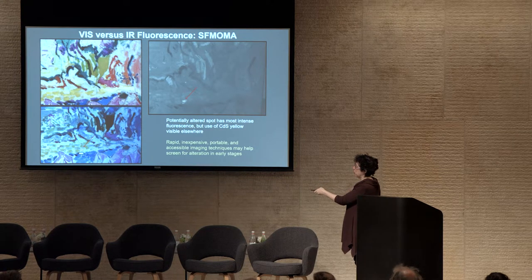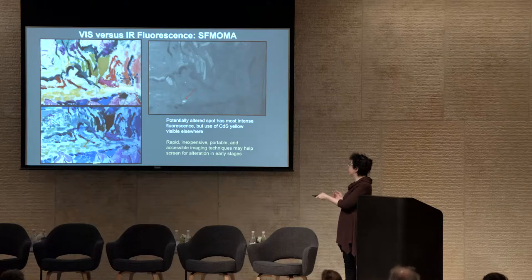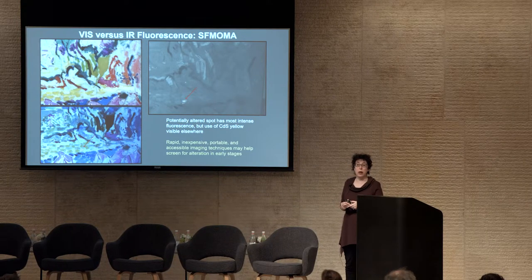The same thing is true in the area below the central reclining figures — that one brush stroke that looks a little dirty shows up as orange in ultraviolet light and as bright white in the infrared. Even if you just have an ultraviolet light you can buy on Amazon for about $30, we have an incredibly accessible way to understand the state of preservation of these paintings. This problem is largely confined to the period from the 1880s to the 1920s but has become a phenomenal problem for the works of the Impressionists, Post-Impressionists, and Fauves. We can quickly identify areas where photo degradation is going on, and then get into the micro analysis to understand whether it's a photo oxidation or a photo reduction, because how we preserve the painting depends on the mechanism.